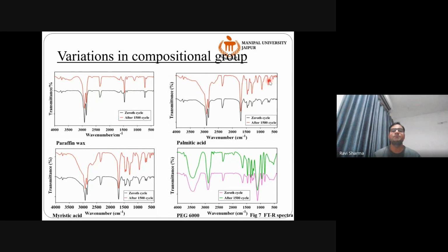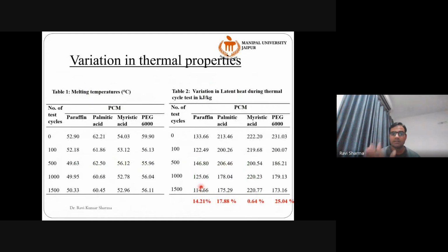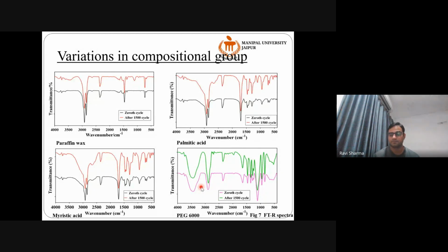Now these are FTIR curves, Fourier transform infrared spectroscopy. These curves tell us about the functional bonding of these materials. You can spend a few moments looking at what happens after 1500 cycles of each. I won't go into more detail since this is deep chemistry which might bother you. Just look at the peaks, and you'll see that the shape of peaks after 1500 cycles is almost similar to what it had at the 0th cycle. That simply means there are no changes in the functional behavior of these materials after 1500 cycles. Chemically, the material is very, very stable. We see thermal stability here, and chemical stability here.